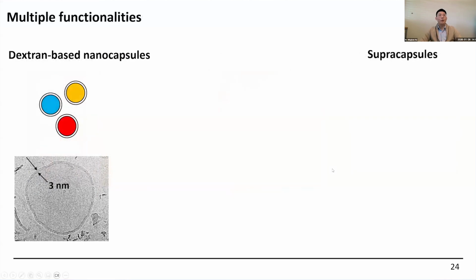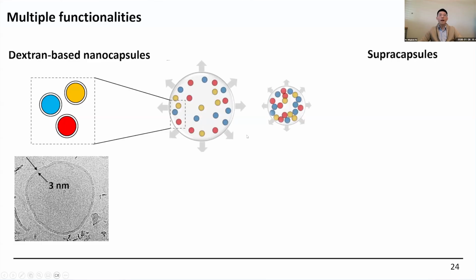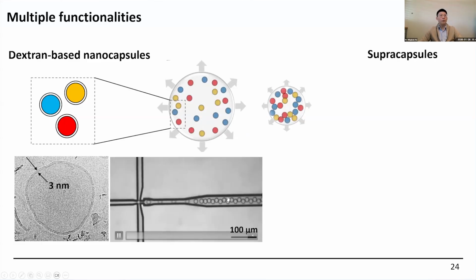But the next thing I would like to talk about is to make it have multiple functionalities. And to do that, instead of using the single nanoparticle as the building block, we use the dextran nanocapsules as the building block. Because the nanocapsules can carry cargoes inside, we can have more functionality within these cargoes. And here what I show is we use the dextran-based nanocapsules because they are biocompatible. And then we use microfluidics to generate the droplets. Within the droplet, we have the dextran nanocapsules with different cargoes.